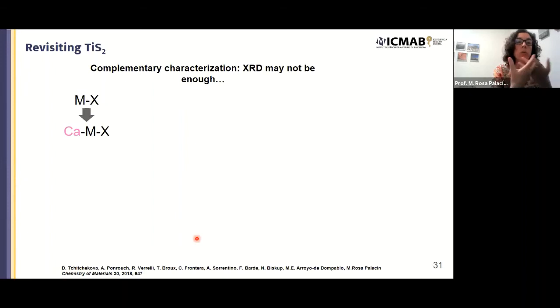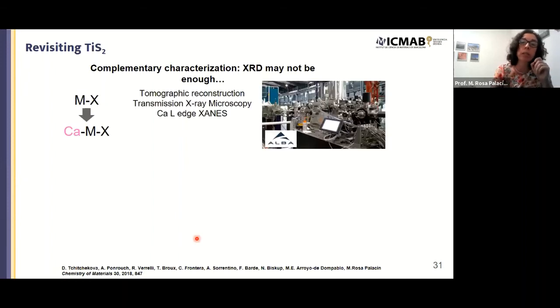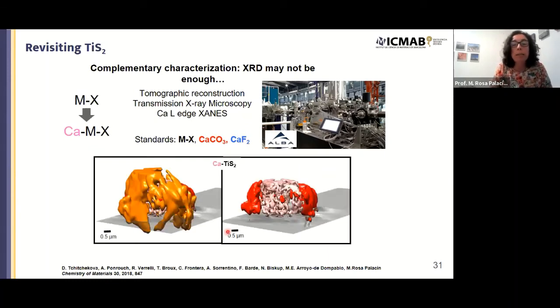So in this case, we looked for complementary characterization techniques, and luckily enough, we were able to do synchrotron experiments at ALBA and do some transmission X-ray microscopy at the calcium L-edge and do some tomographies of the particles. We used a standard, the pristine TiS2, and also some compounds that can form as a result of the electrolyte decomposition, such as calcium fluoride or calcium carbonate. And this is what we get.